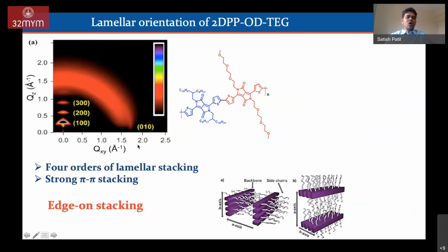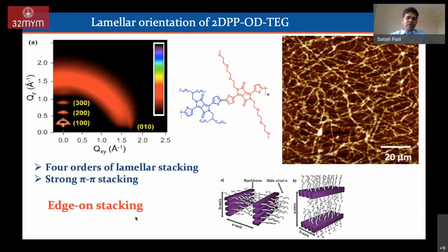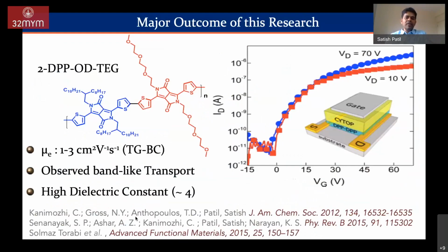So there is very strong pi-pi stacking interaction, and the polymer predominantly forms J-stacking, which is very good for the transport properties. When you cast a film and look at the AFM image of the thin film, we see it forms a bundled surface, and the substrates are not treated substrates. So it is simple casting of a film on SiO2, and you see long nanofibers of these structures. And eventually, as I said, I will not go into much detail in the interest of time.